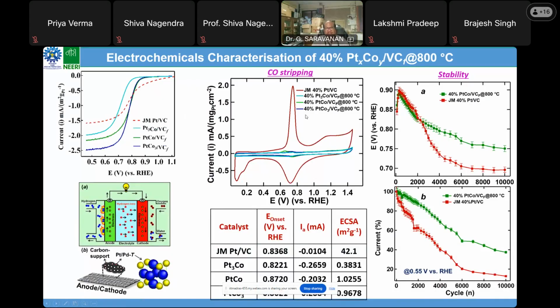Okay. We also checked the CO stripping characteristics using the Johnson-Matthey catalyst. As I pointed out, with commercial catalysts, if CO gas is present in the hydrogen stream, it can adsorb, and the activity will not be there if there is CO. But with the catalyst that we developed here, there's no CO adsorption on the surface, even under CO rich conditions. Also, this catalyst will work under these typical fuel cell conditions.